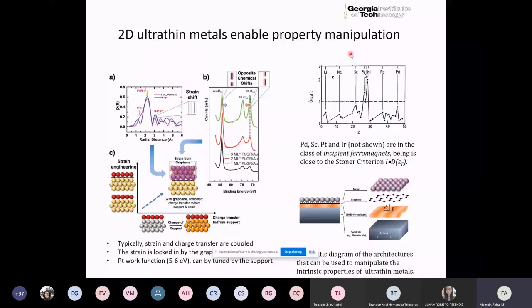The second thing we could do is control the strain on the platinum by the graphene. The graphene itself, as long as we could figure out whether or not the graphene actually transfers strain on the platinum or not. In other words, can we grow platinum as a film on graphene? If we can, then the strain condition would come from the graphene. And if the strain condition comes from graphene and is locked in by graphene, then that would be separated from the charge transfer effect that you could control from the other side of graphene by a different material. So in other words, we could do strain engineering on the one hand, and we could do charge transfer engineering along another axis.